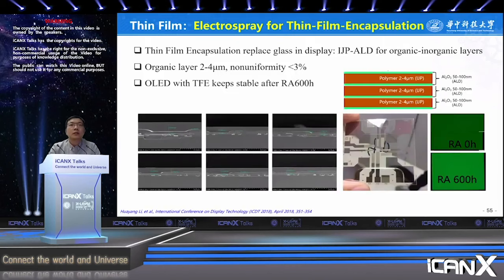And very important, the flexible display has high deformability, so it's difficult to encapsulate it with a glass sheet like the traditional display. The flexible display is usually encapsulated by an organic or an inorganic layer. Thin film encapsulation replaced the glass in flexible display. Printing the organic layer gives a thickness of 2 to 4 micrometers, and the nonuniformity is less than 3%.